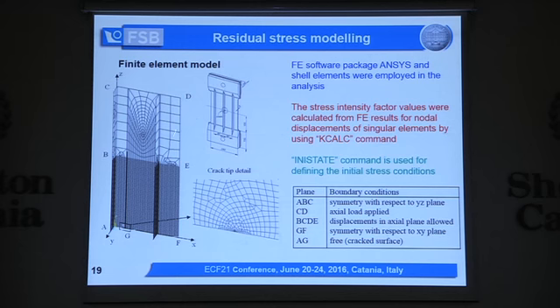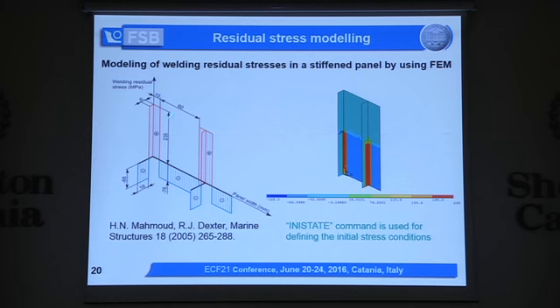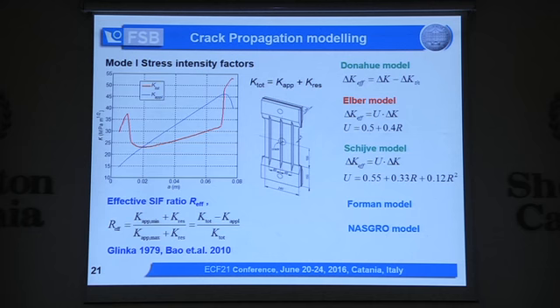So we introduce residual stress into our stiffened panel and calculate the stress intensity factors without residual stresses and with residual stresses. So at first we consider rectangular, and residual stress are introduced here. And then we calculate stress intensity factor. This is without residual stresses, and this is with or including residual stress. You see that at short crack length, initial crack length was 2.8 millimeters, but it's much higher due to residual stress, and here is lower. And then we use these K values to simulate fatigue life.